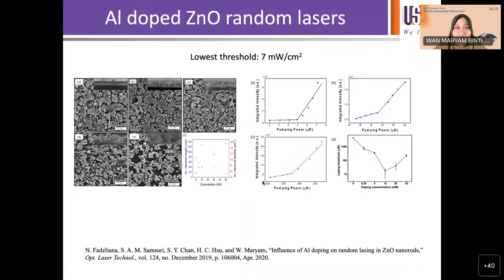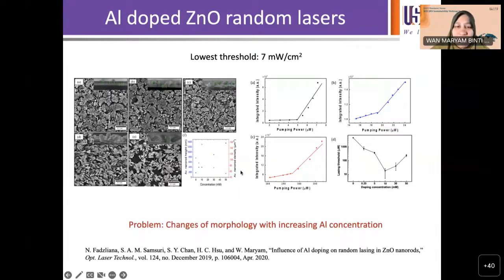And so this is when we started doping our zinc oxide. When we dope, we notice that yes, we see a reduction in threshold at a certain doping concentration, which is 10 millimolar in this case, still using the same method of chemical bath deposition. The only problem is, as you can see here, the size of the structure changes drastically as we increase the doping, because you are working with a concentration that is varied. So you have the issue of changes of morphology, right?